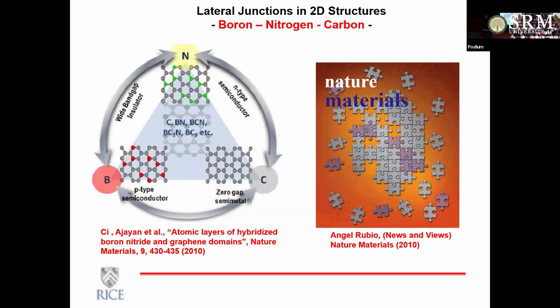But anyway, we were fascinated by this three-component system: boron, carbon, and nitrogen. And we wanted to actually make it, because people had already made graphene, people had already made boron nitride. We wanted to see if you could make a BCN three-component system in a single atom thick layer. So we did that experiment, did vapor phase synthesis with precursors containing boron, nitrogen, and carbon. And instead of forming this thermodynamic phase, that is BCN, what we actually got was a mixture of phases, boron nitride and carbon. The boron and nitrogen atoms tend to come together, and carbon tends to come together, and they form these patchwork, essentially a quilt-like architecture. Again, all in a single layer.